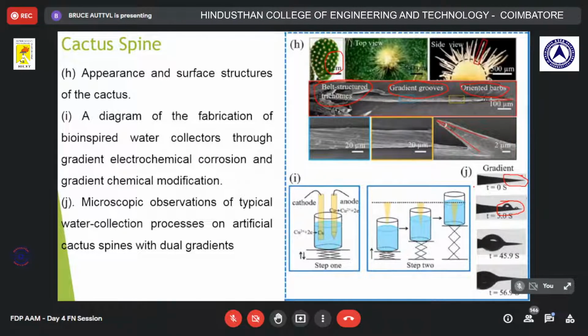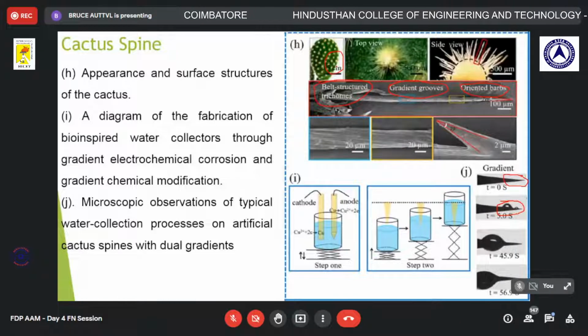Okay, so even on this surface, in the cactus, the microscopic observations have revealed a structured grooved path in such a way that the water droplet can be collected in a regular fashion and nourish the plants evenly. Specifically, the droplets on the surface of the cactus spine are usually driven to the side with a larger radius due to the gradient of Laplace pressure, and the microgrooves on the spine are sparser at the base. So less rough at the base and more rough at the tip. This gradient roughness produces a gradient surface free energy, which generates the driving force to drive the water droplet toward the base of the spine.